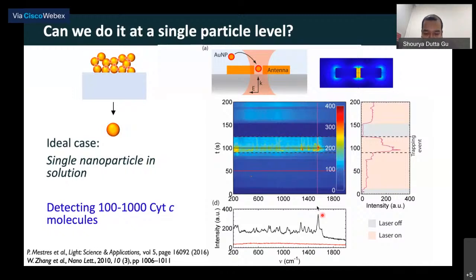And then this is the spectrum that you see in the trapped region and you see very nice peaks, right? Now, if you actually calculate a rough estimate of the number of molecules, you will get around 100 to 1000 molecules on each of these plasmonic particles, right? So what you're basically doing, you're reducing the amount of molecules from millions of molecules to barely 100 or 1000 molecules on a single particle, right?